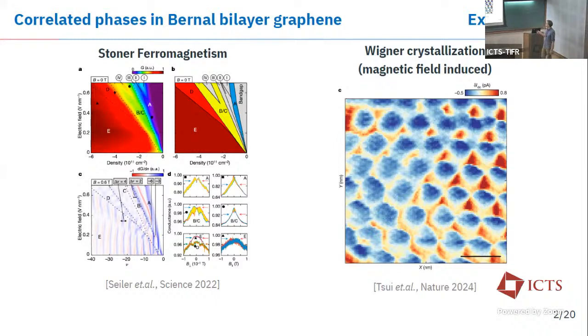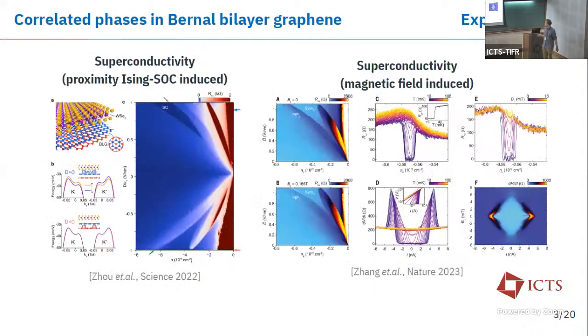Very recently, some other charge instabilities have been discovered using STM in Bernal bilayer graphene, and here you see a picture of a Wigner crystal that is induced by a magnetic field that you put externally in Bernal bilayer graphene. And notice the scale bar here. I haven't put the actual scale, but this is 50 nanometers. So this is a huge length scale where you see charge ordering of that material, and it's expected that non-local electron-electron interactions play a very important role. And the length scale, furthermore, is that large because in reciprocal space, the Fermi surface of the material, or the pockets of the material, are tiny, which we're going to see shortly.